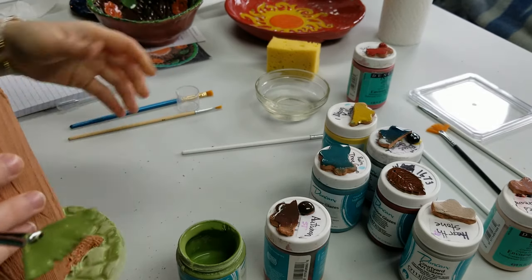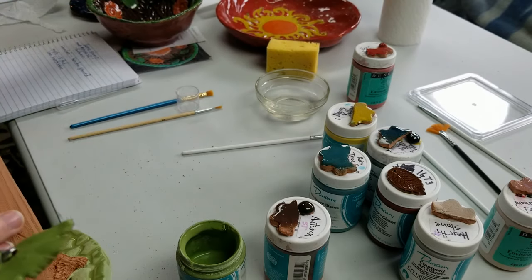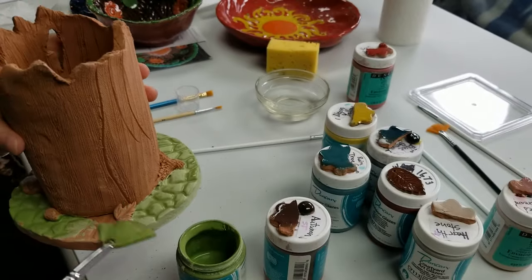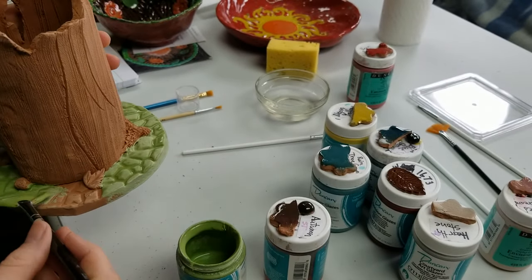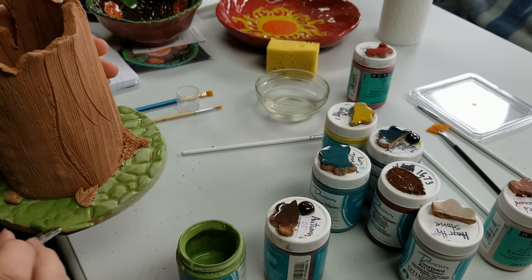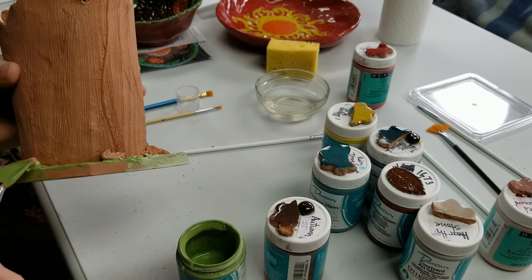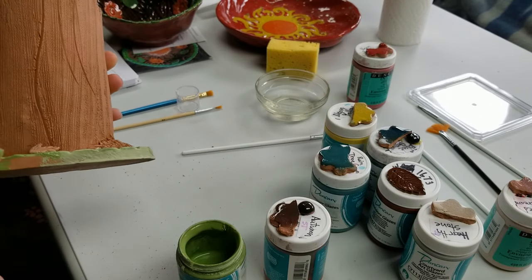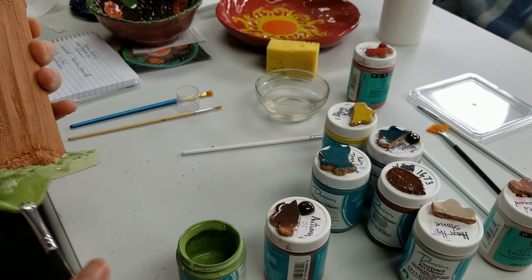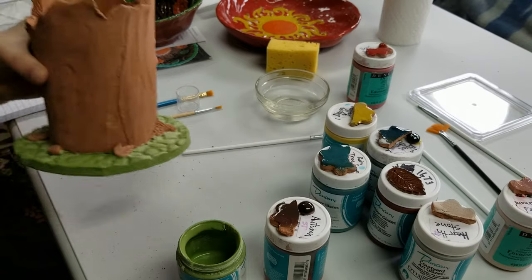Well, I'm doing this on a side note. When it comes to your crystal glazes, so your fruit punch or something like the night frost there, if you do them, don't put them on the bottom inch of your piece because they have a tendency to drip. And if they get onto the kiln shelf, they basically weld themselves on. And then the lovely person who did it gets the lovely chore of taking a Dremel to it and fixing the shelf or replacing the shelf, which is not cheap at all.